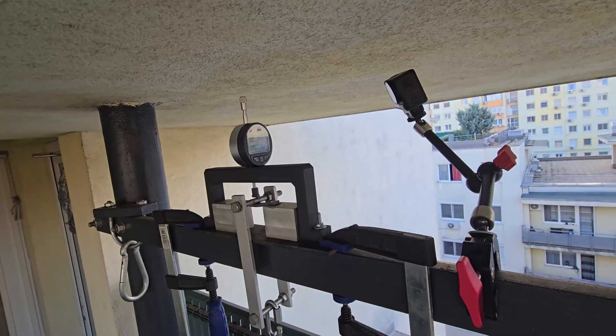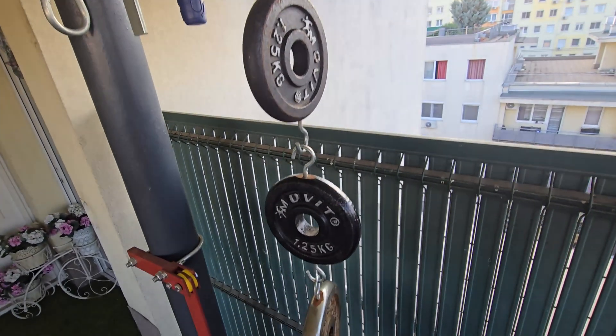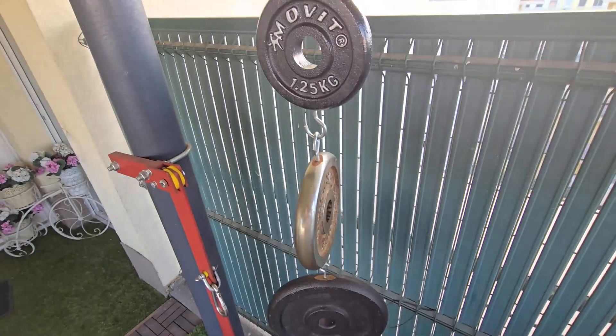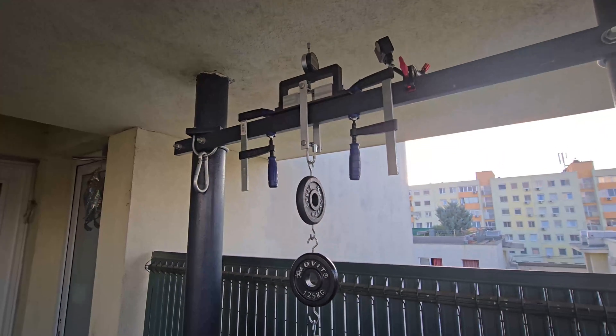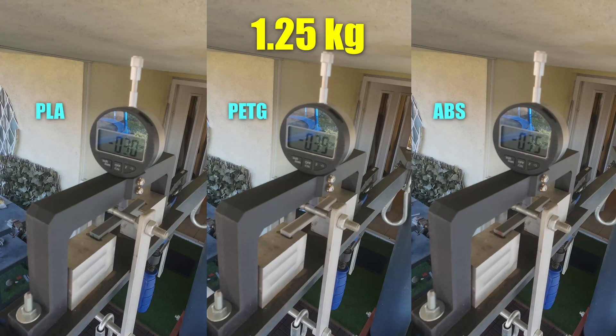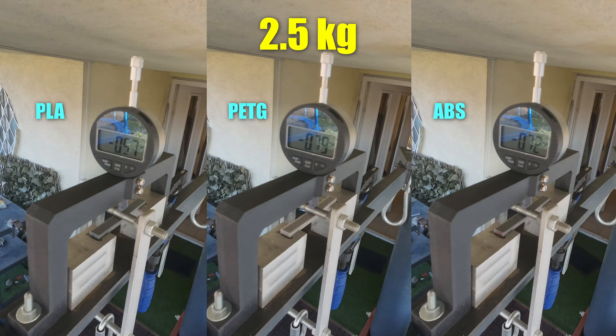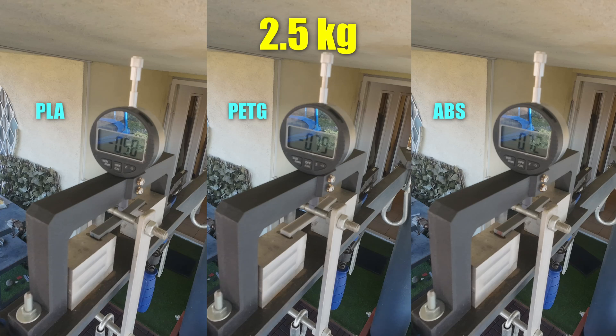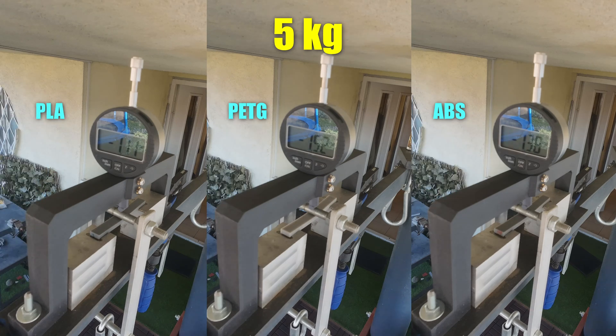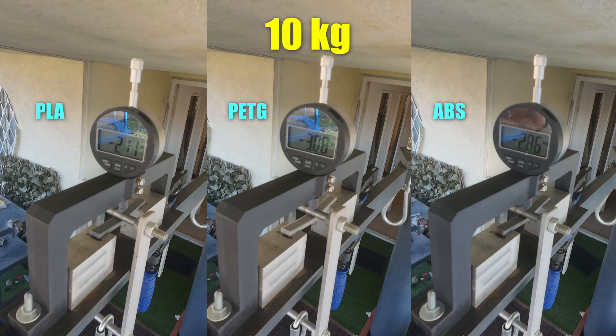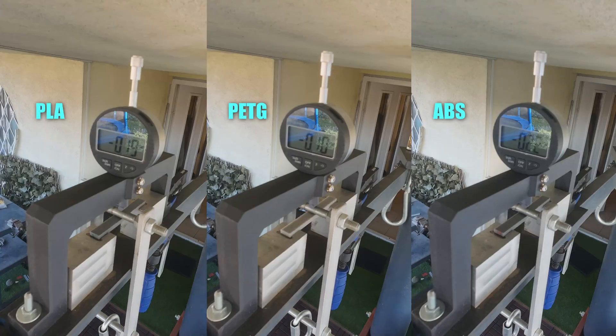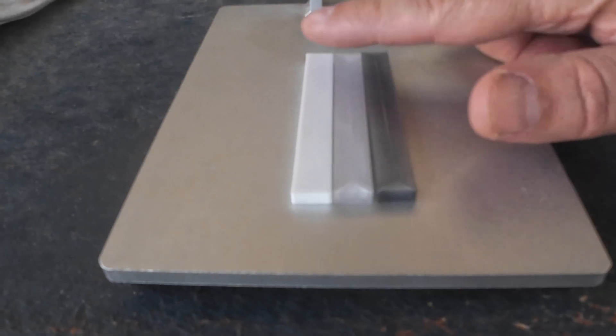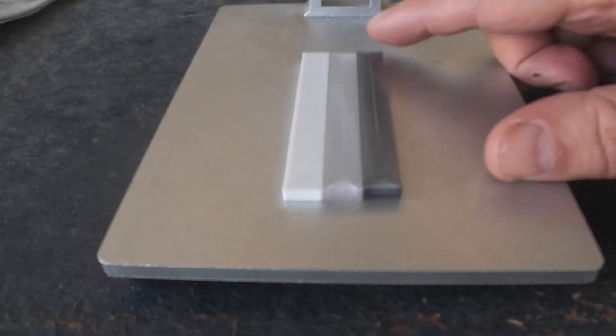Three-point bending test where I'm measuring the deformation under these loads which I will place one by one, measuring the deformation after 1, 30, and 60 seconds. Side by side all three materials. This is under 1.25kg, under 5kg, and under 10kg—you can see the constant deformation on some objects. After the test, no permanent deformation on the test objects.